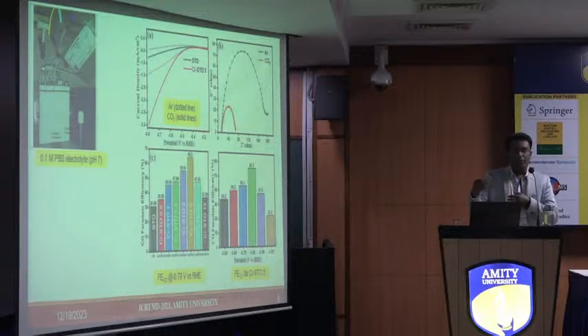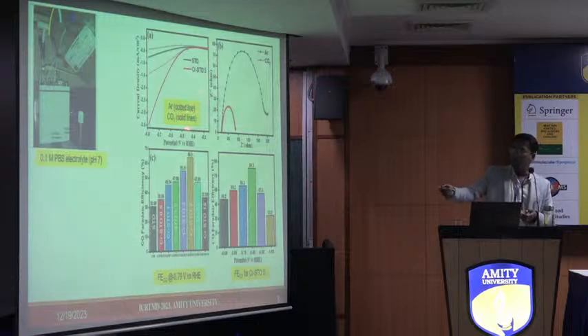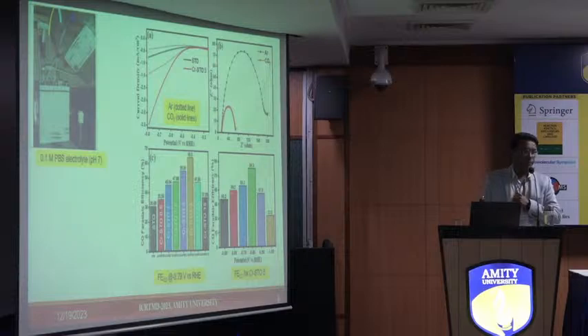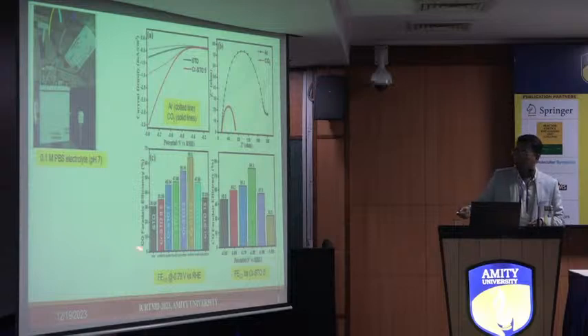Which means that the electrode is sensing something. So what it's generating is actually converting carbon dioxide into something, and we are not sure what that something is. For that, we collect all the gases coming from this and characterize them with gas chromatography. The gas chromatography tells us that there is a formation of majorly carbon monoxide.